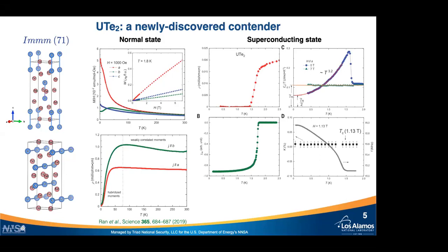The heat capacity is very interesting too. Here we have a clear peak at TC, but it's interesting that at low temperatures, the Sommerfeld coefficient, or the low temperature extrapolation to zero temperature of the specific heat, is actually quite large. It's about half of the normal state gamma. I'll put a pin on this for now, and I'll come back to this later. It's still not very well understood why that's the case.